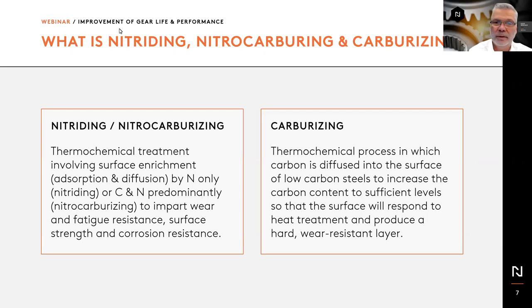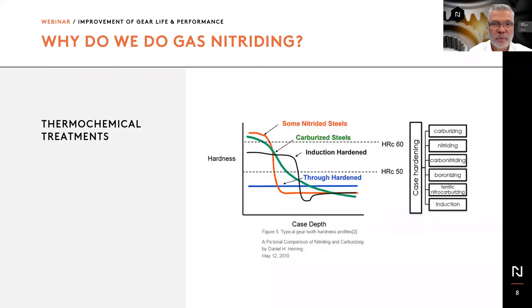Carburizing relies on the diffusion of carbon, and the diffusion of carbon at a much higher temperature allows for a subsequent heat treatment, which consists of a quench and temper. And quench and temper temperatures, of course, will modify core hardness as well as surface hardness, and the amount and the depth of diffusion of carbon will define the case obtained on the carburized component. This is the main difference, and obviously those curves don't really represent 100% of applications.